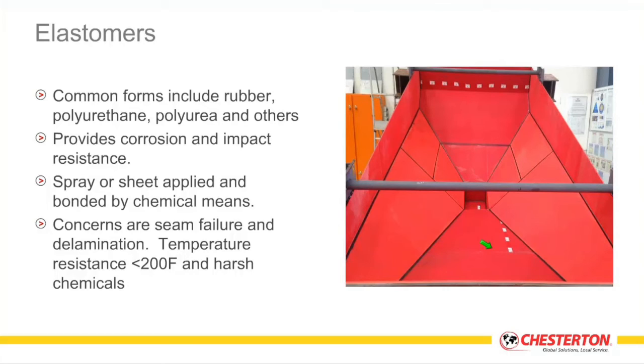first, and once that undercuts, then the seam is exposed, and then rapid delamination of the surrounding sheet layers can occur. Again, when these materials fail, it tends to be in sheet format, and these sheets can then break loose and become part of the process flow, binding up a valve, binding up an impeller and a pump, or a rake arm and a thickener, and cause further downstream damage. So you want to be concerned about the mode of failure with these types of materials as well.